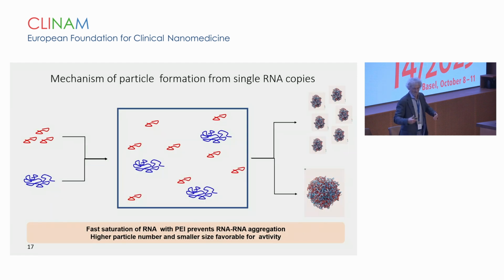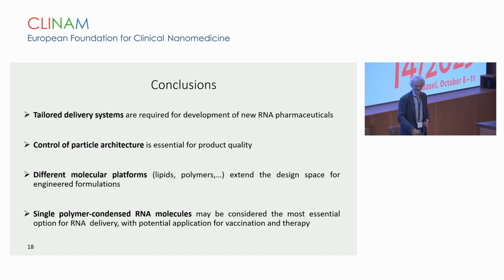What's the foundation? It's basically polymer physics. So it's a polymer electrolyte complex where the aggregation conditions depend on the concentration and on the relative concentration of the moieties. So what we do is we provide a large excess of PEI and a very low concentration of RNA, and by that we saturate the large RNA molecules with the PEI, and we then increase on the first hand the number of particles, and we make them smaller, both favorable for activity for certain applications.